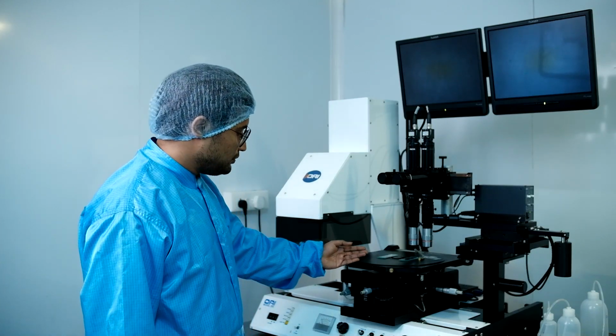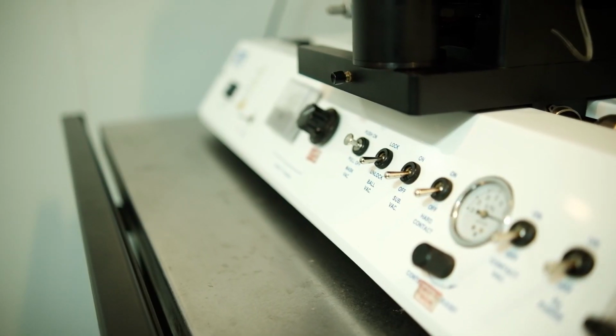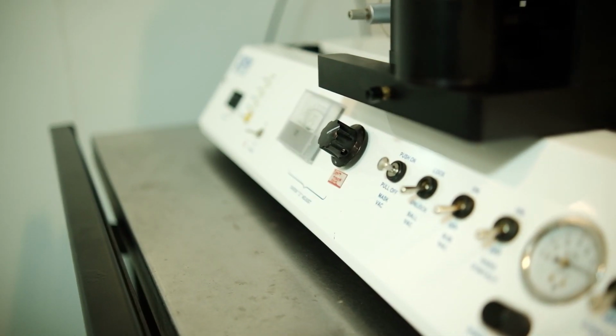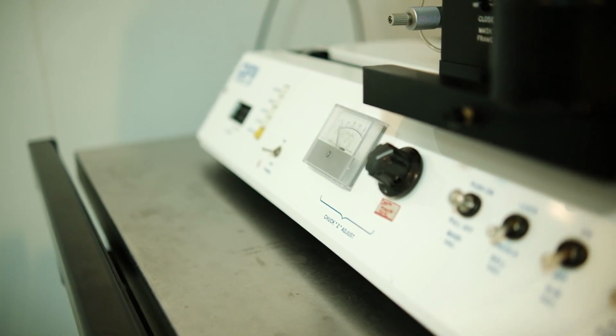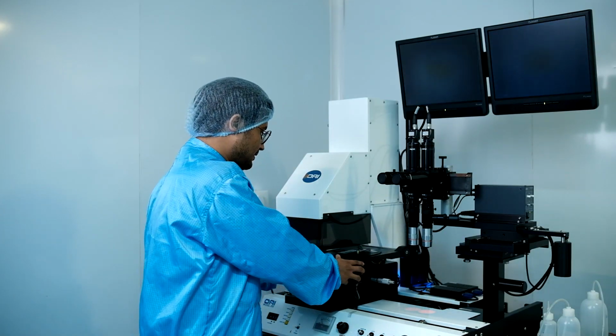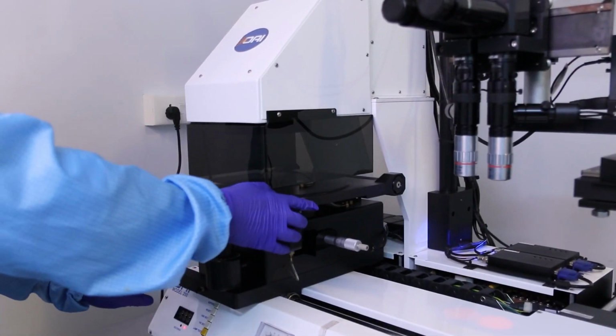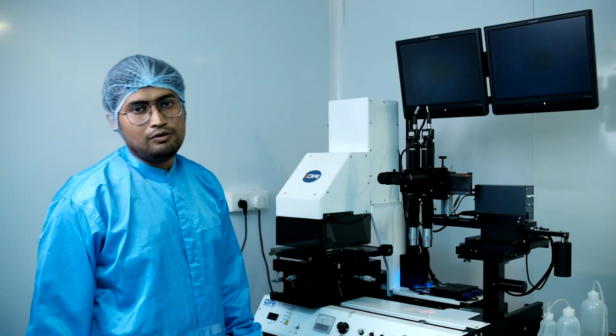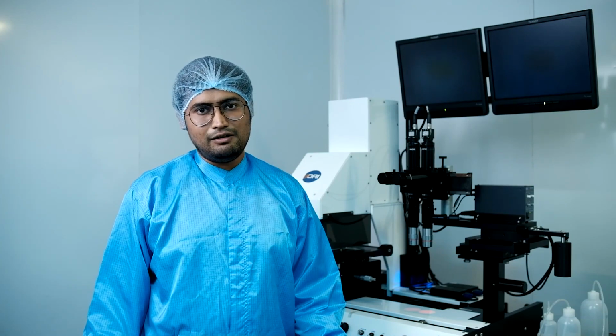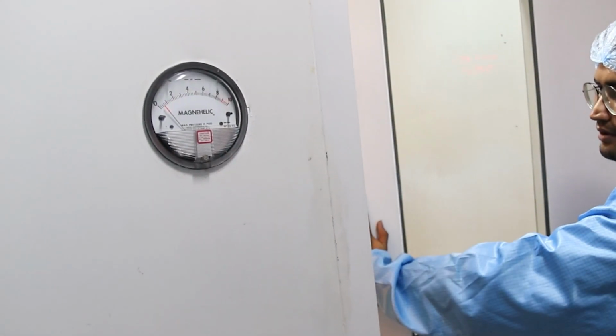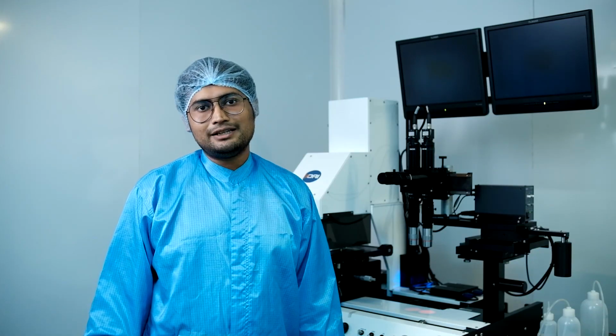What we do is use a vacuum pump to hold the substrate, then we place our mask over it and expose it under the UV light. For the photolithography process, we need to take care of two things. One, the room should be at positive air pressure. Number two, the light should not react with the photoresist material which we are coating.